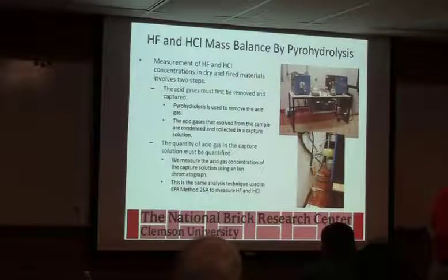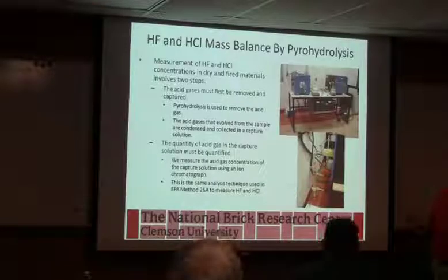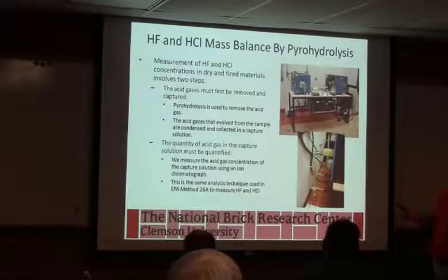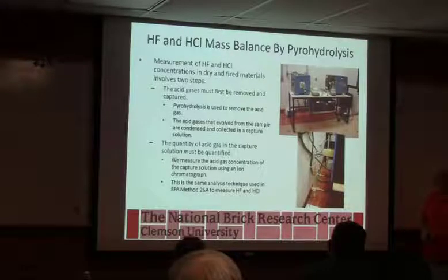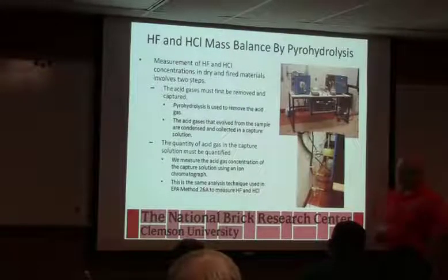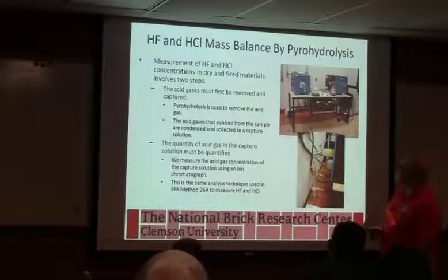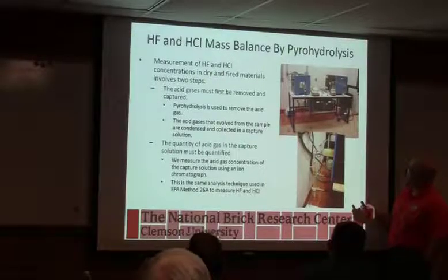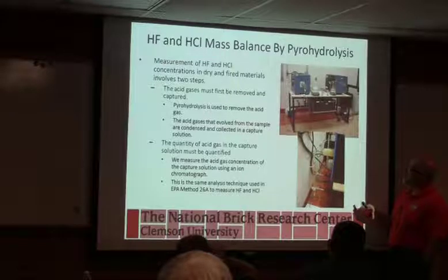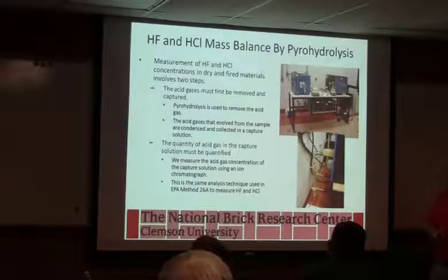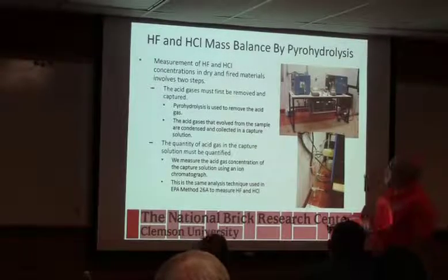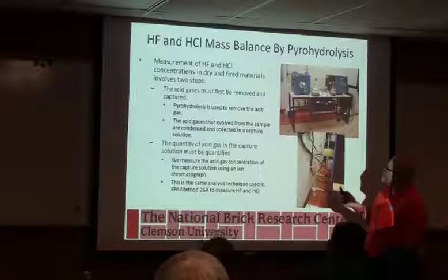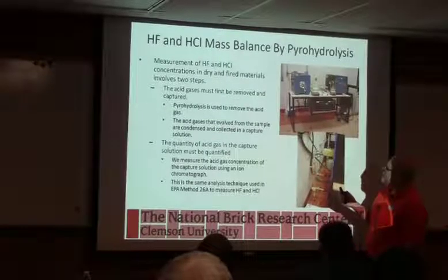So, like I said, we do balance measurements, and this is actually a test I lifted from when I was looking for a way to measure fluorine and chlorine. It's so small, it's hard to get it out, it's hard to measure it. But this is called a pyrohydrolysis. I stole this idea from the people who deal with nuclear salts. They want to know the fluorine content in uranium salts, and they came up with the method. But basically, we heat the sample up in a tube.